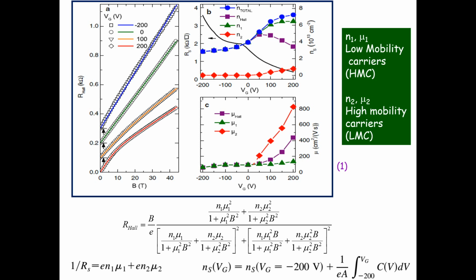So now, if I add N1 and N2, that is my total, here, the round circles. The N1 and N2 that I get from my two-band model, if I add the two, this is my curve, and it turns out that it matches exactly the carrier density that I get essentially by using the charging formula for a capacitor. Okay, so this is the charge I am putting in at the interface, and that adds up to N1 plus N2. So the question is, where are these high mobility carriers and where are these low mobility carriers? So we have to look at the electronic structure of the interface.